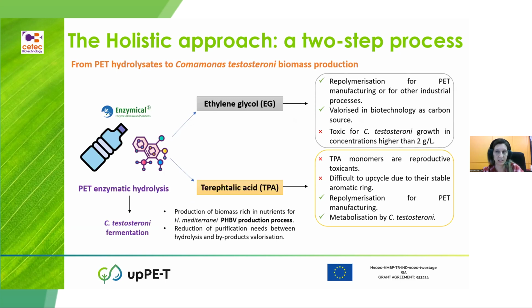Well, the holistic approach is a two-step process. From the PET enzymatic hydrolysis, we can obtain two monomers, the ethylene glycol and the terephthalic acid. This ethylene glycol could be repolymerized for PET manufacturing or for other industrial processes. It could also be valorized in biotechnology as a carbon source, but in our process it is toxic for Comamonas testosteroni growth in concentrations higher than 2 grams per liter, which is the maximum concentration that we can feed our microorganism. On the other hand, the terephthalic acid, the TPA monomers, are reproductive toxicants, and they are very difficult to upcycle due to their stable aromatic ring.